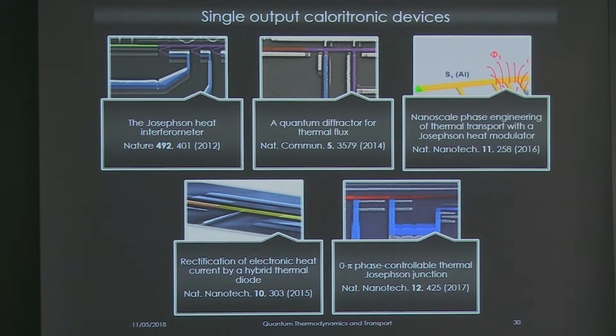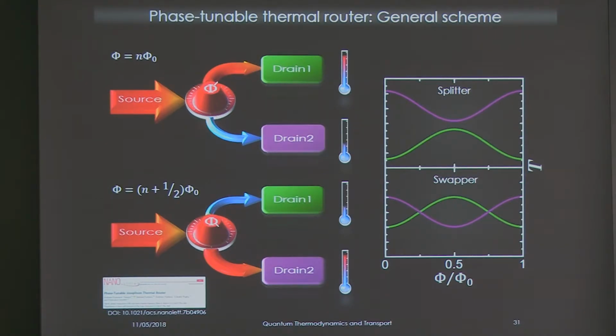Very important to show, for instance, if it is possible to do a sort of thermal routing system. So what is a phase tunable router? It is just a system. This is a general scheme. We have a heat source that goes inside a sink, and then we have a phase tunable object that is able to separate the heat carrier from one side to the other. So to enhance, for instance, the temperature of one drain with respect to the other for integral values of the flux. And for semi-integral values of the flux, according to all the effects that we have shown, this temperature here, for instance, can be smaller than the other.